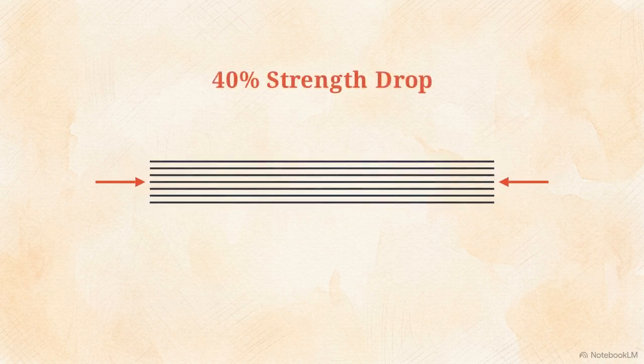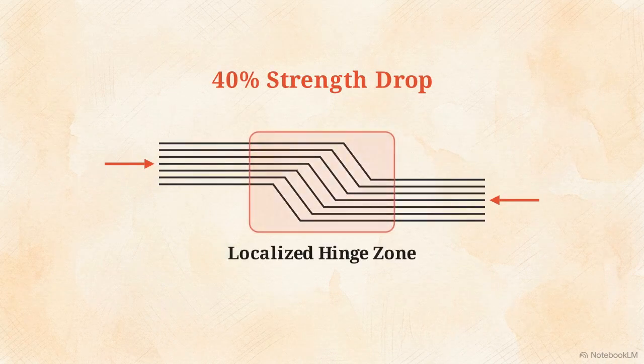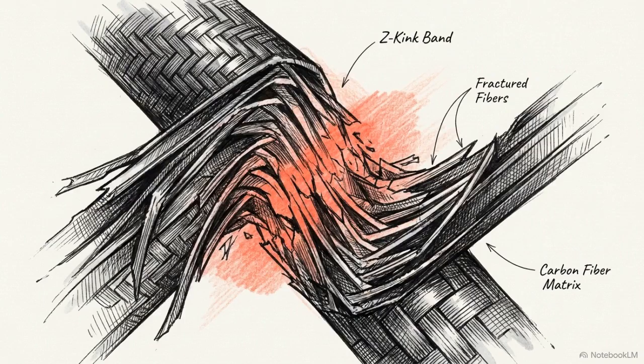When squeezed longitudinally, the material's strength can drop by 40% compared to its tensile limit. This drop is caused by a failure mode known as fiber kinking. Instead of compressing evenly, the internal microstructure suddenly collapses into a localized hinge.